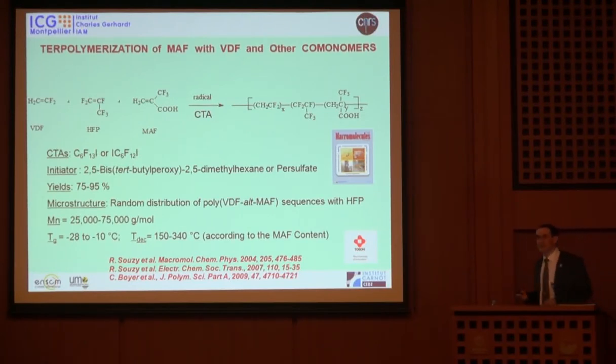And what was very interesting, by NMR, I don't show you NMR today, but we have a random distribution of alternating structure between VDF and this MAF, this alpha-trifluoromethyl acrylic acid, so it's a block of this alternating copolymer separated by one HFP because hexafluoropropylene does not homopolymerize.